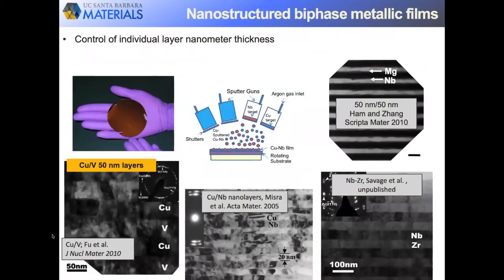So you may notice that despite these very fine nanometer layer dimensions, the layer morphologies are highly regular. They have a uniform layer thickness, very well controlled periodicity. And this is possible because these nanolayer composites have been deposited. They were built from bottom up, atom to atom, if you will. These samples overall are thin. They come as about several hundreds or a few hundreds of microns thick, or tens of microns thick, I'd like to say.